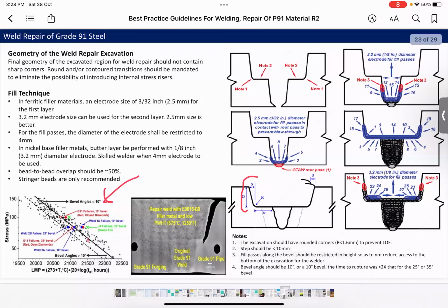And the angle, as I said, should be 10 degree to 15 degree. This angle, if you see this chart here, shows the comparison between different angles. The joints were tested with different bevel angles, and it shows that with 10 degree bevel angle, the time to failure was double the time required for 25 or 35 degree bevel.